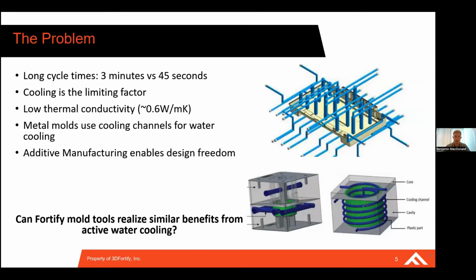With our material, the real limiting factor is cooling, but that's due to the thermal conductivity. So our thermal conductivity is on the order of 0.6 watts per meter Kelvin, which is an order of magnitude lower than steel and 2 orders of magnitude lower than aluminum. So looking at that value, we're really not in a good starting position to actively cool our tools. It's still possible. We're still able to transfer heat from our tool into water, but it's just going to be at a slower rate.